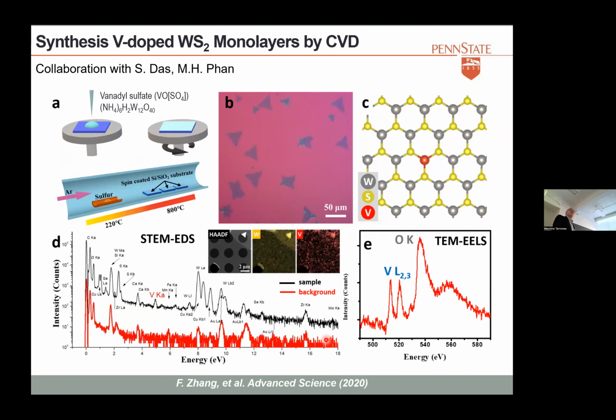One thing we did was with vanadium. The reason why vanadium is very interesting is because we can dope and we can alloy with vanadium. We can start with 0.1% of vanadium, but we can go all the way to 15% vanadium. So that gives us a very long range, and we can start monitoring the properties as we introduce vanadium into the system, and that's what we did.